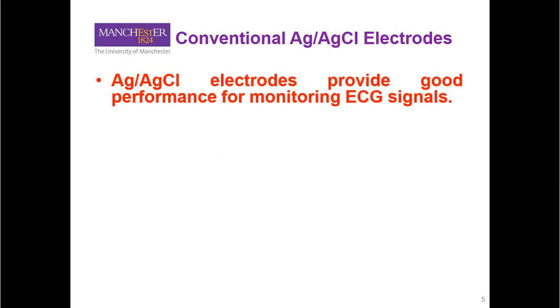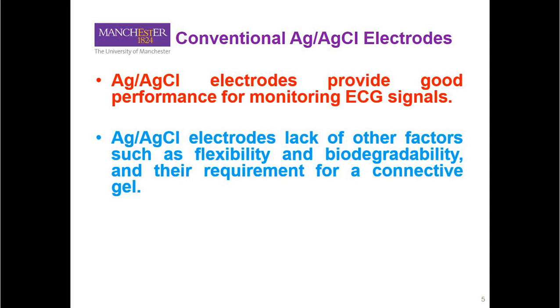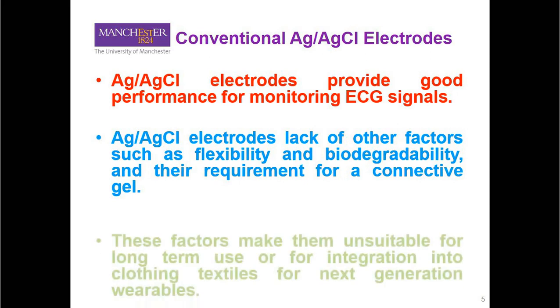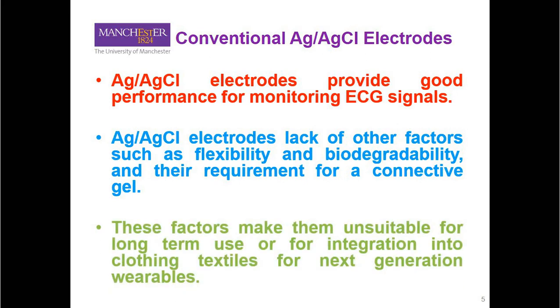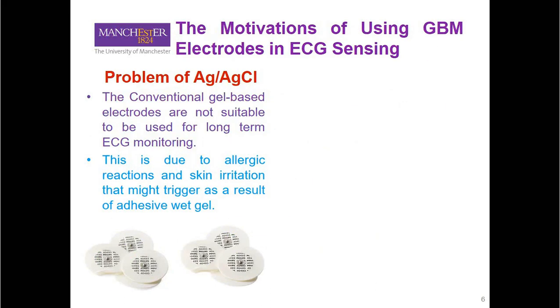Although the silver chloride electrode provides good performance for monitoring the ECG signal, the lack of other factors such as flexibility, biodegradability, and the requirement for a conductive gel make them unsuitable for long-term use or for integration into clothing textiles for next generation wearables. And here I would like to talk about the main limitation of the gold standard silver chloride. The conventional gel-based electrodes are not suitable for long-term ECG monitoring, and the reason is the allergic reaction and skin irritation that might be triggered as a result of the adhesive wet gel.